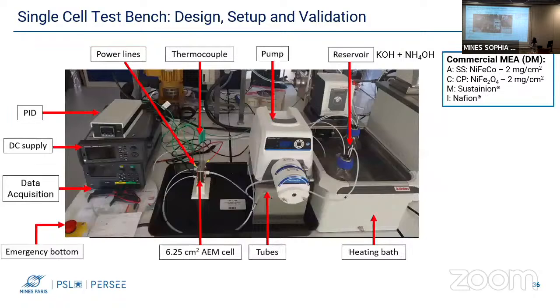This test bench consists of an AEM single cell provided by Dioxide Materials and dedicated to water electrolysis applications. It has an active area of 6.25 centimeters squared and is provided with a commercial MEA containing nickel-based catalysts, an anion exchange membrane, Sustainion, and Nafion as a binder.